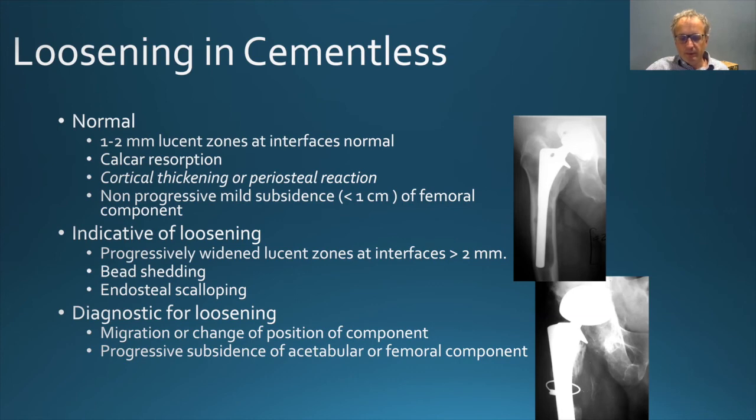And the other problem is that sometimes with these cementless hips, you put them in, but you've undersized them, and they then sink down the femur, and then they get secondary stability, secondary fixation later, but further down the leg. So in your first post-op x-ray, they might be where you wanted them to be. And then at your one year x-ray, they're 2 centimetres down the femur, but they might not be loose because if it doesn't go any further, it's stuck.